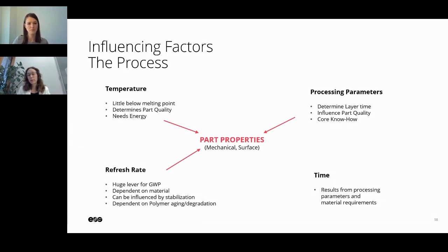Looking at the processing parameters, they're dependent on the temperature, on the refresh rate, and on the time. Depending on how the temperature is set, I have to add more laser energy or less laser energy. Depending on what refresh rate I'm running, I have to adapt my process in order to work with aged powders. But then again, the temperature and the refresh rate influence each other as well, because if I'm able to process my polymer powder at a lower temperature, I can, for example, use a different refresh rate because I'm aging my powder less.